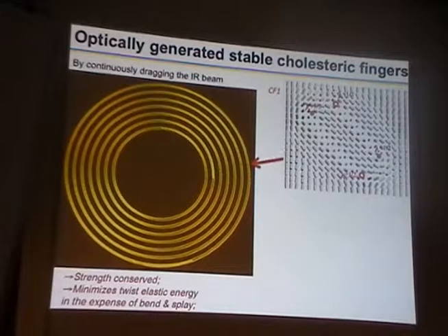And so as we do it, we can generate two structures. One of them in this location is called cholesteric finger of the first type. And in a sense what we have in here is a quadruple of non-singular lambda disclinations, right? Minus lambda minus 1/2, 2 of them here and here, and lambda plus 1/2, right?